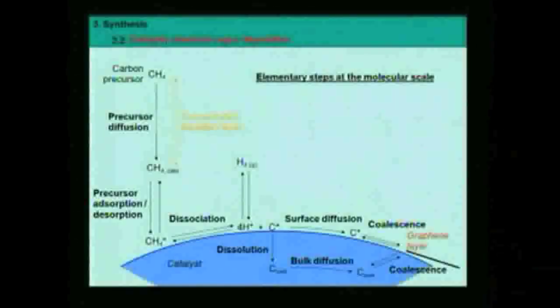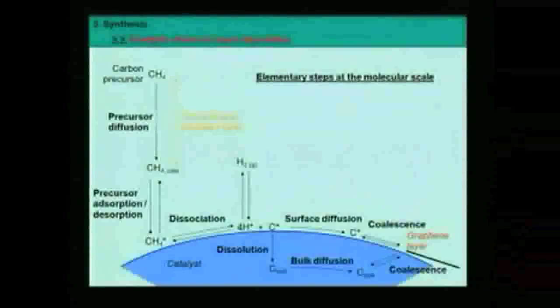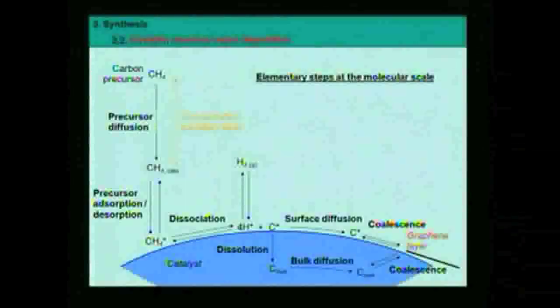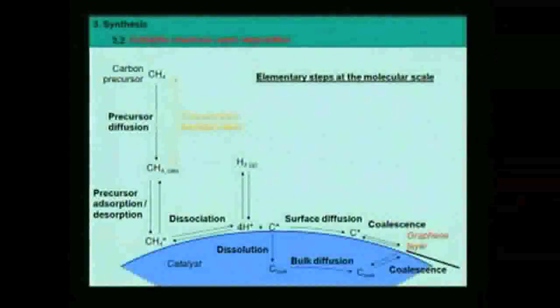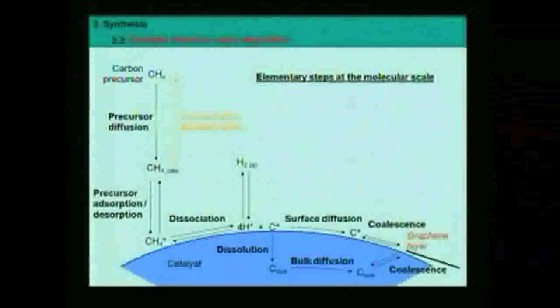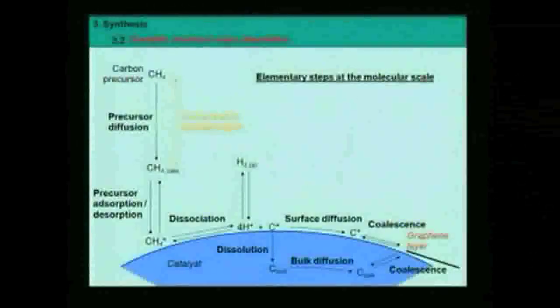Okay, sorry, so I keep going. We can have either surface diffusion or bulk diffusion. Then those carbon atoms can meet and form large islands of carbon by creating sp2 bonds, and then a graphene layer or a nanotube can grow from these elementary atoms. So this is just to give you an idea of the different chemical reactions involved in order to grow at the end a carbon structure at the surface.